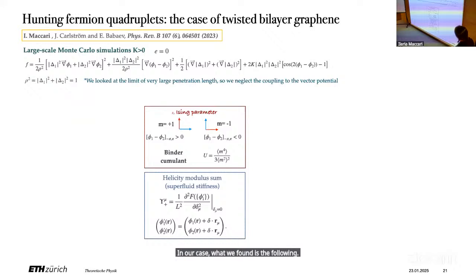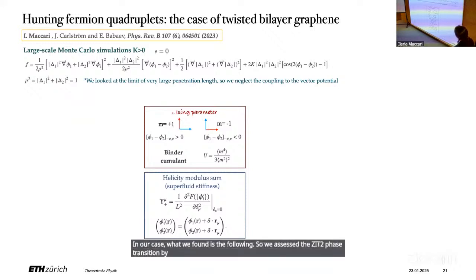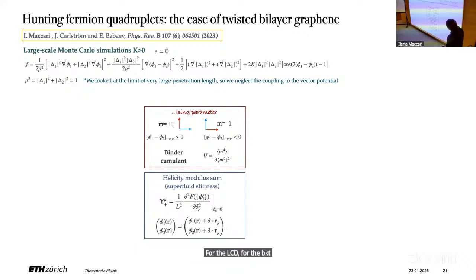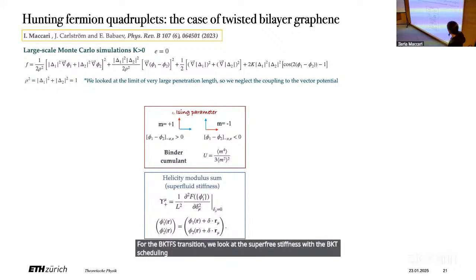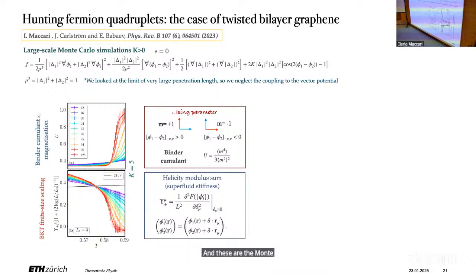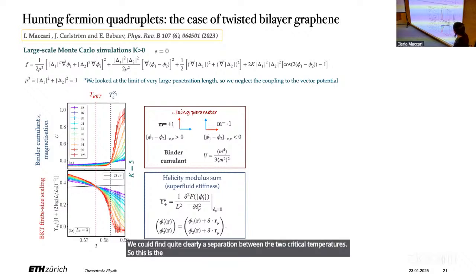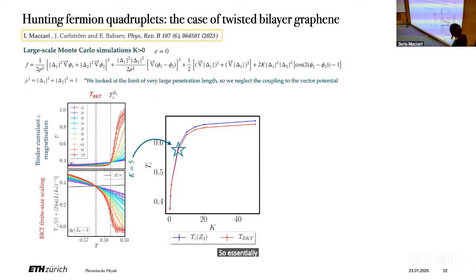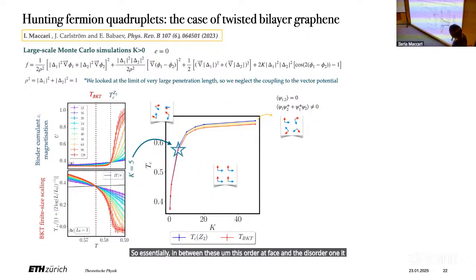We assessed the Z2 phase transition by defining an Ising parameter for the two chiralities and by computing the Binder cumulant. For the BKT phase transition, we look at the superfluid stiffness with the BKT scaling associated with the phase sum. And these are the Monte Carlo results. As you can see, for different linear sizes of the system, which is the way to extract the critical temperature, for this value of K we could find quite clearly a separation between the two critical temperatures. So this is the BKT, and this is the Z2. Essentially, in between the ordered phase and the disordered one, this fermion quadrupling condensate appeared.